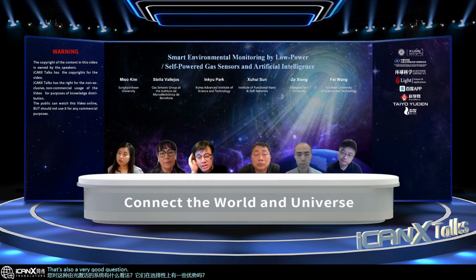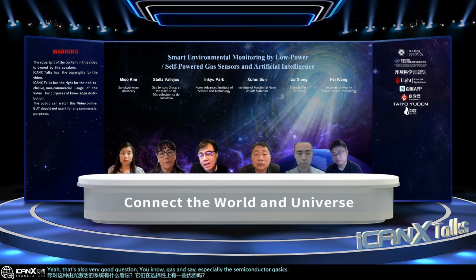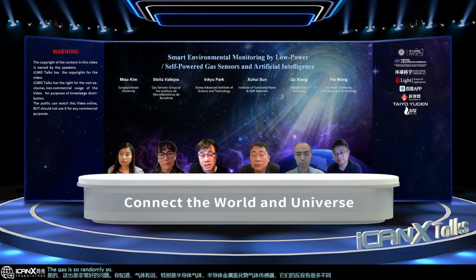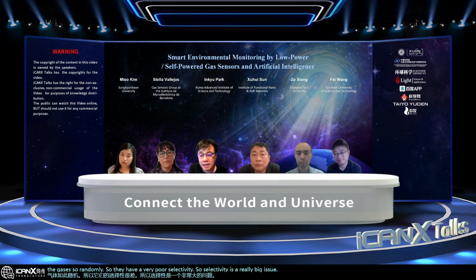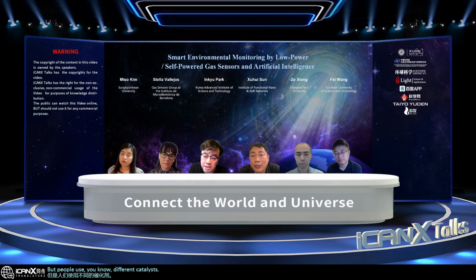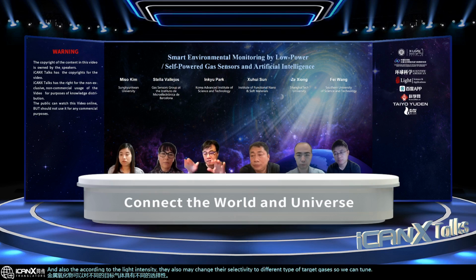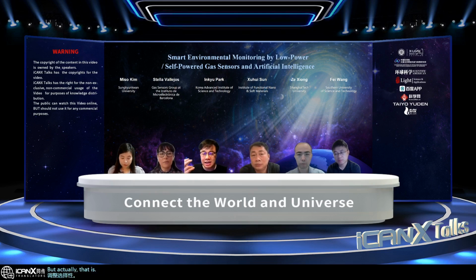Yeah, that's also a very good question. Gas sensors, especially the semiconductor metal oxide gas sensors, react with a lot of different gases so randomly. So they have a very poor selectivity. So selectivity is a really big issue of the semiconductor metal oxide gas sensor. But people use different catalysts that can be more sensitive to a particular type of target gases. Also, depending on the operation temperature, the metal oxide may have different selectivity to different target gases. And according to the light intensity, they also may change their selectivity to different types of target gases. So we can tune the intensity of the light to tune the selectivity, but actually that does not give a full answer.